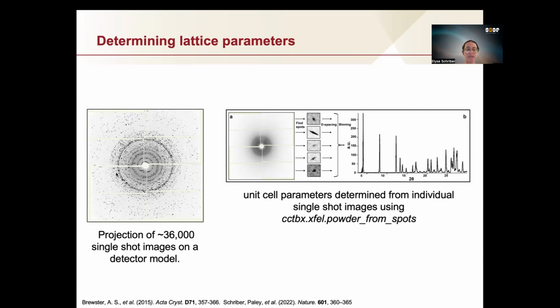Now, one could try taking the radial average of that powder pattern, but as you can see here, there's a lot of pathologies that show up, and this is because a lot of microcrystals are suboptimal. And what makes SFX unique is that we can work with these suboptimal crystals that are not as high quality as you would get from a single crystal experiment. What's not great is that the diffraction pattern itself reflects that poor quality by showing spot pathologies. The spots might be smeared. You can see some actually very robust smearing in this pattern here. And it becomes very challenging to extract unit cell parameters from that.